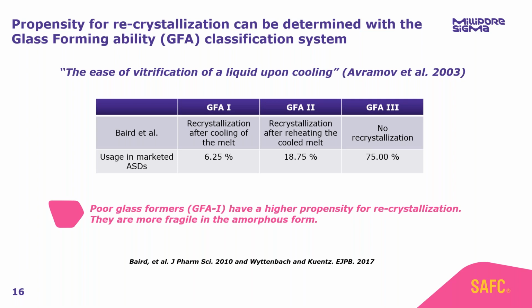These molecules are very comfortable in the amorphous form and have a low risk of recrystallization. In the middle, we have our GFA class 2, our moderate glass formers. These molecules remain amorphous in the first cycle, so they can be melted and cooled and not recrystallize. But as soon as you start to melt that system again and supply a little bit more energy, then they recrystallize, so you observe a melting endotherm. So these molecules have a moderate stability in the amorphous form, a moderate propensity to recrystallize.